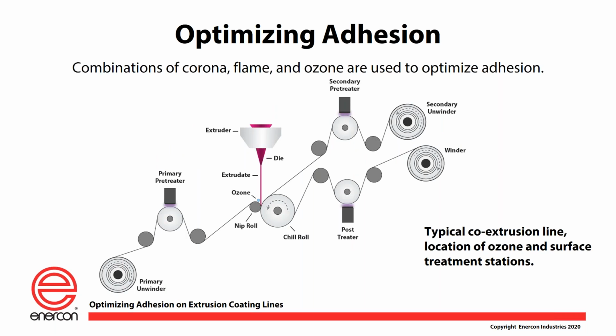When you want to optimize the adhesion in your process, you will look for surface treating equipment in a variety of locations along the line. For example, we unwind a primary substrate. That substrate typically has to be surface treated prior to its first introduction into the process. That primary treater could be a corona treater, or it could be a gas flame treater. Depending on what your primary substrate is, that may determine what piece of equipment goes in that primary treat position. Let me give you an example.